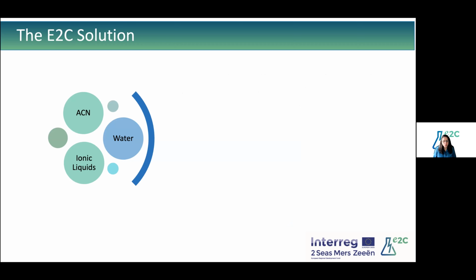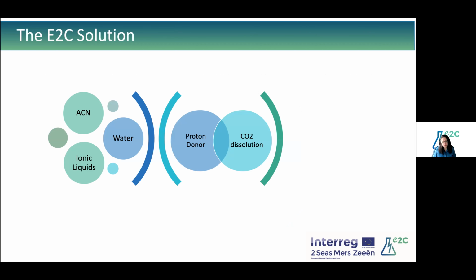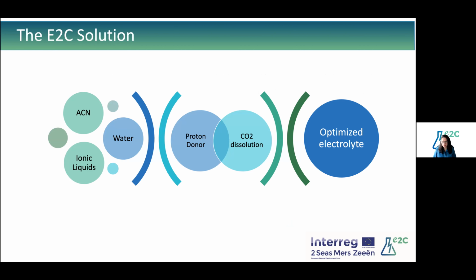So for the E2C solution, we're proposing a mixture of acetonitrile, water, and ionic liquids. The goal here is to tailor the proportion of proton donors in the system and the availability of CO2 in the system as well by improving its dissolution. Ideally, we're aiming to reach an optimized electrolyte, which would have the perfect proportion between proton donor and CO2 dissolution in the system.